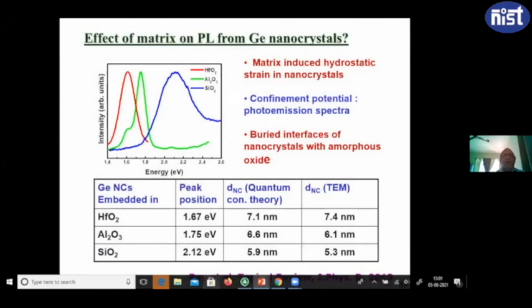Yeah, in this case, germanium nanocrystals were taken either in a silicon dioxide matrix or aluminum oxide matrix or hafnium oxide matrix. Only the band gap has to be high, and you get the light emissions at different wavelengths. This is just to show that this works not only for silicon dioxide, but for different kinds of materials.